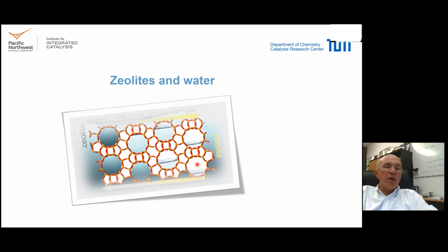In a naive way, one would think that if we add water to a zeolite and we add sufficient pressure, we slowly keep filling the pores until we have a homogeneous water-like environment. I will show you that this is not the case, and that there is a distinct stop at one point, and that it is very tricky and difficult to fill pores with water completely.